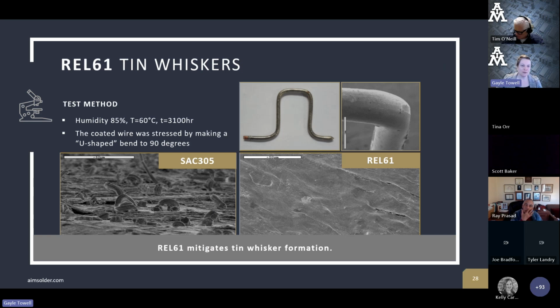Tin whiskers are something that happens sometimes with SAC or other tin-based alloys. Essentially, you put some stress and strain on something that has tin, and these little whiskers start sprouting up. And that's a problem, obviously, because that can create conductive paths that you don't want to be there. So one thing we've noticed is, for whatever reason, probably due to the bismuth content, it somehow mitigates the tin whisker growth. We performed this test. We had these coated wires with these two alloys. We bend them, we stress them, and we look for tin whiskers. SAC305 has them, REL61 does not. So if that's a concern in your production, rest assured, REL61 doesn't seem to have that problem at all.